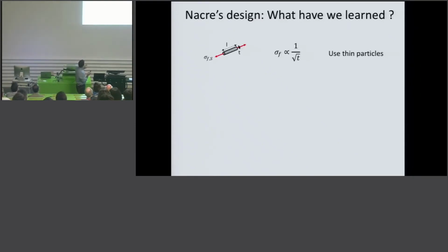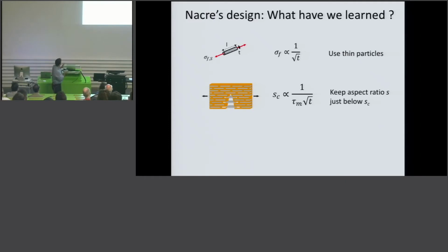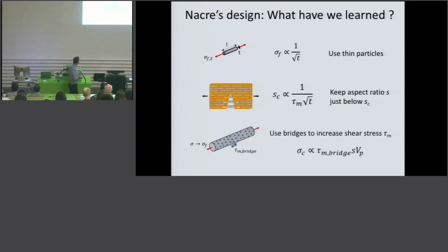So just to wrap up really quickly for the design, what we really want is to make the platelets as small as possible, so making them thin is good. And we want to design their shape so that they're elongated enough to carry load, but not too elongated that they would break, right? And because the matrix around these platelets is just too soft, we want to add mineral bridges in order to increase the shear being transmitted to the platelets.